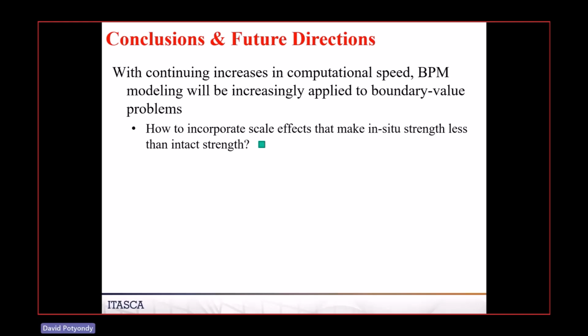diameters. In both cases, the metric you're interested in is the number of grains, the number of particles across the diameter of the hole. That's like a representative scale. And what we find is that as you get more and more particles across that diameter, it gets weaker. My understanding is the same thing occurs in perforations and boreholes, where if you make your borehole bigger and bigger, it gets weaker and weaker. So we are seeing that same sort of effect here, a size effect that's just naturally occurring.